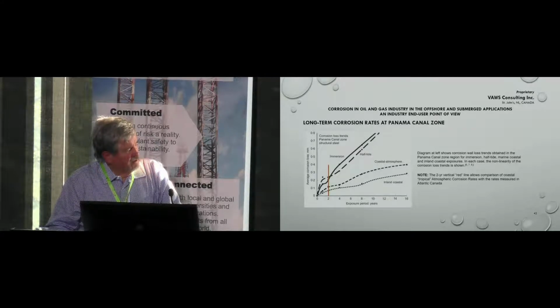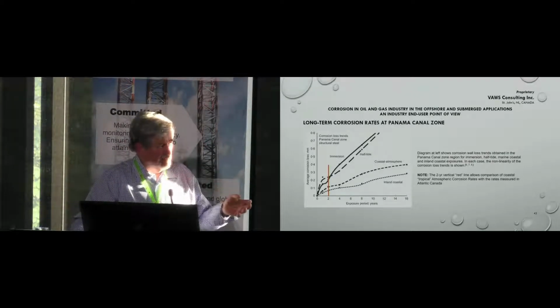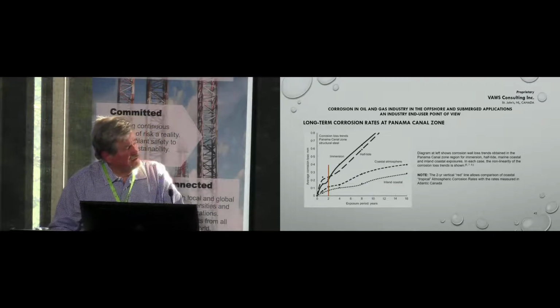And you can see that the corrosion rate at 2 years was relatively comparable, but compared to us, the corrosion increase in the case of Sable Island was decreasing with time, because as the corrosion layer grew on the samples, the corrosion slowed down. Here you see the effect of tropical environment, temperatures, and no cold air. We tested these coupons for 2 years, and because they were coming down, we stopped testing further. But these people were doing it for 18 years. So you can see that it significantly accelerates in tropical environments.